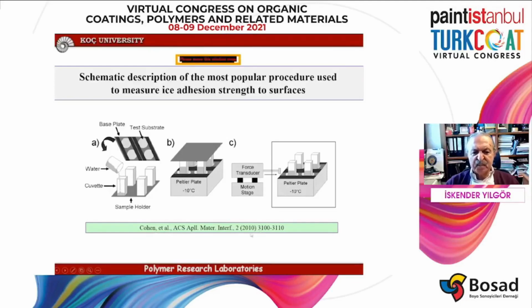This is the paper. You can find the actual procedure in this paper, which is published by MIT and the US Air Force and a few other people. And then you freeze this, and then you measure the force by using a transducer. So this, again, may or may not reflect the actual situation. Why? Because here we are starting with liquid water and freezing it on the surface. However, if it is ice, and you are looking at the turbine surface, this really doesn't mimic that system. But this is the conventional method that most people use. We also use the same thing in our labs.